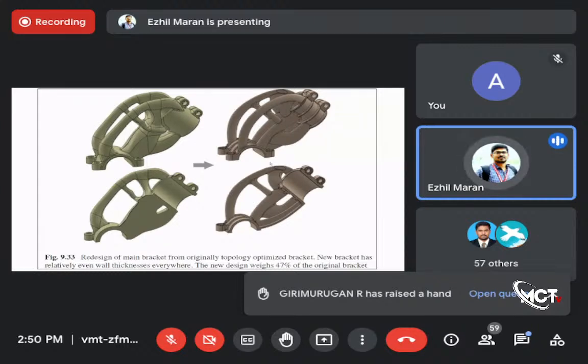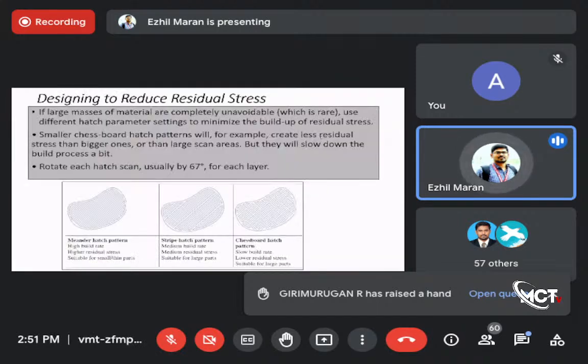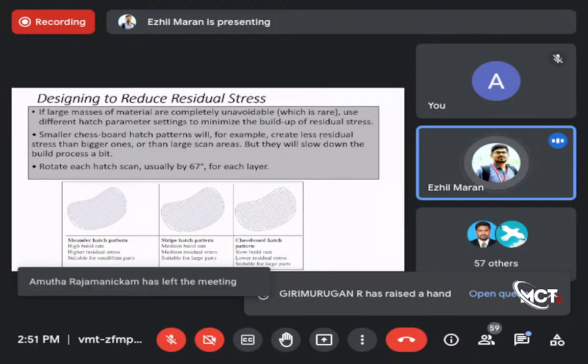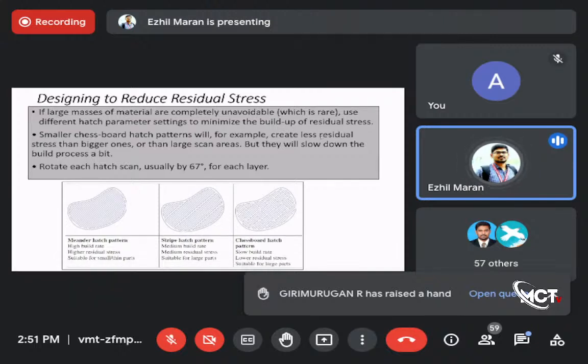There is a design-wise idea to minimize the residual stresses. The first is the meander hatch pattern. The second one is the stripe hatch pattern. The third one is the chessboard pattern. There are a lot of these patterns present, but the third one, the chessboard pattern, will predominantly improve the material strength by minimizing residual stresses. That chessboard hatch pattern is mostly recommended for any product manufactured by 3D printing.